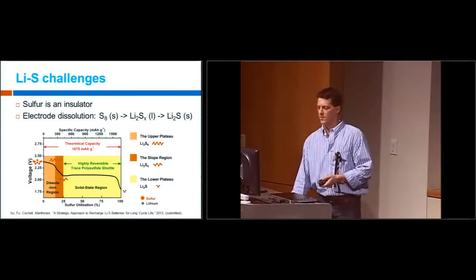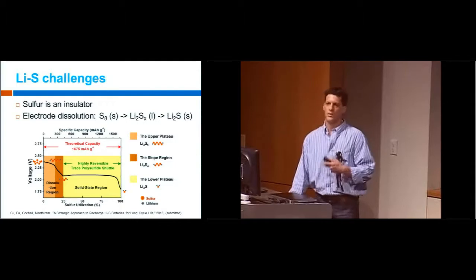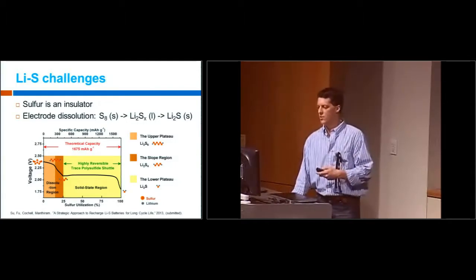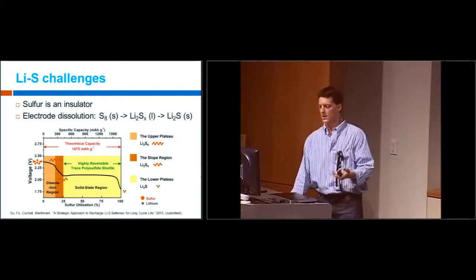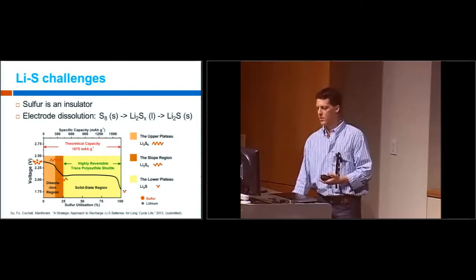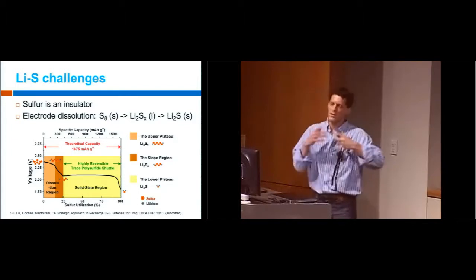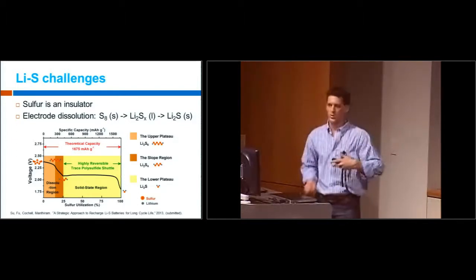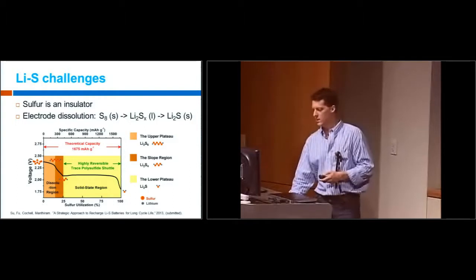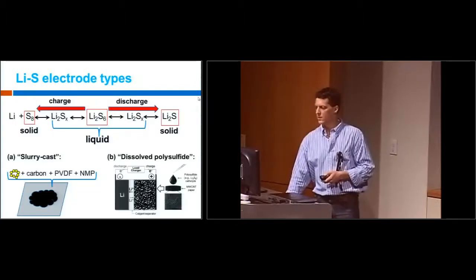Now this creates a variety of problems. Number one, you have to find some way to encapsulate the sulfur in a conductive matrix, a conductive material. Second, if you want to retain the full capacity of the battery, you have to find a way of preventing the migration of the liquid substances, because they dissolve and move out of the cathode, and then you lose that material and it's not available in subsequent cycles.